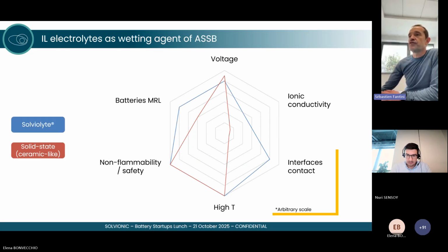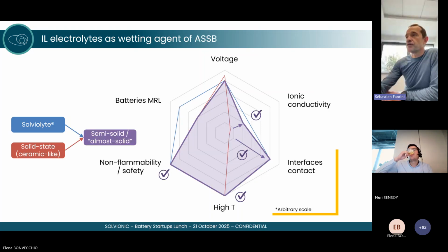But when you use the ionic liquid instead of conventional liquid electrolyte, then you still improve the conductivity and the interface contact, but without losing any safety aspect and any high temperature ability to work with solid state electrolyte.